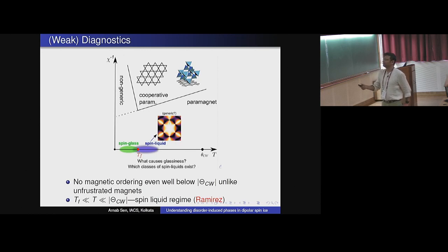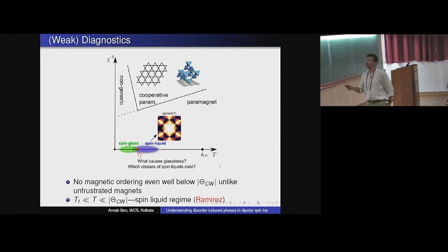And basically, the important thing here is that unlike a ferromagnet or an antiferromagnet, these points here in momentum space are not Bragg spots, so they don't identify any long-range ordering. Rather, if you look carefully, if you move in different directions in momentum space, you realize that these are points of discontinuity in momentum space, and these are called pinch points, and basically that signifies that the spin-spin correlations in real space are algebraic and don't develop a long-range order, okay?